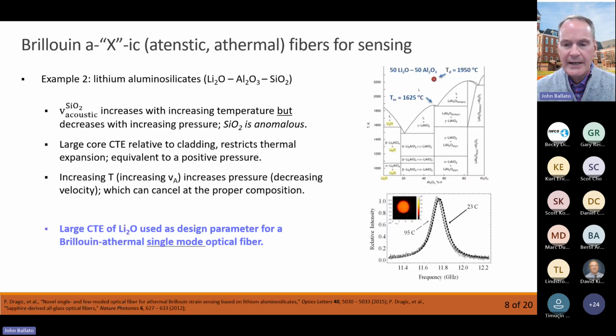This is a slightly more complicated one, but again, it works. All of these are done in silica. All of these are done using commercially scalable methods. So this is a lithium aluminosilicate. This is a little bit different, as I said, where you're playing with the acoustic velocities and the temperature dependence of the acoustic velocities, and the fact that silica is somewhat anomalous, so that when you heat it up, certain things go in positive directions, certain things go negative. There's also a fairly large thermal expansion mismatch between the core and the clad, and those work in opposite directions. So in this case, you have a similarly athermal fiber from a Brillouin scattering perspective, but it's single mode, which again, you oftentimes need in many sensor applications, so you don't have modedness coming into the behavior. But this is over a wide temperature range, it's Brillouin athermal. So all that you see are strain effects. And there are other versions where they are atensic, which means that you only see temperature effects because the Brillouin is then insensitive to strain.